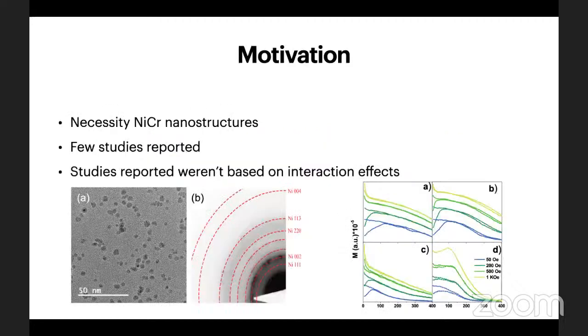Why is a study necessary? It is essential because these structures find a good application in cancer treatment because we can calibrate the Curie temperature to a few degrees above body temperature by appropriate chromium doping. They also have several direct industrial applications. But keeping the bright side aside, to this day, very few studies have been reported on the structural correlation and magnetic properties of these nanoparticles. Therefore, it became necessary to scrutinize their structural magnetic correlation at the nanoscale level. And also, the other few studies reported didn't take interaction effects into account. So in this study, we used a phenomenological model that takes interaction effects into account.